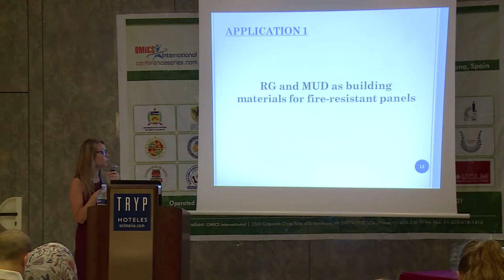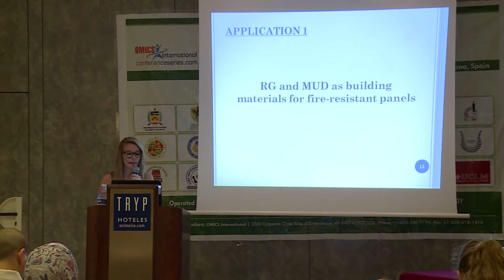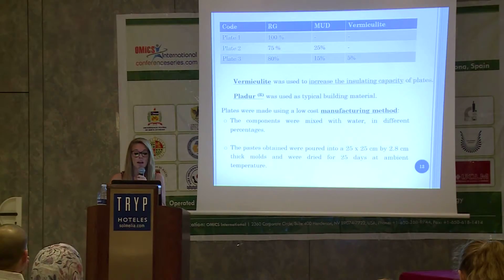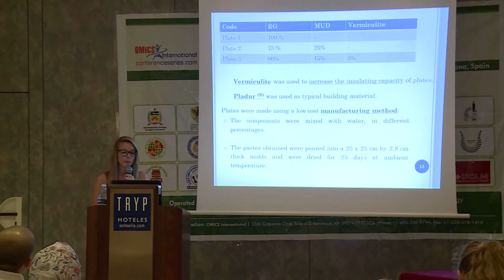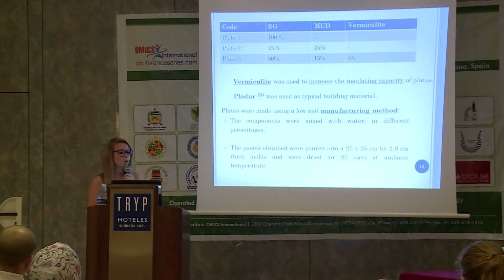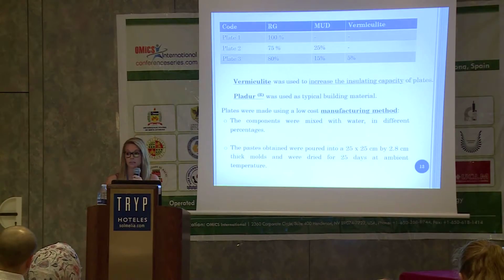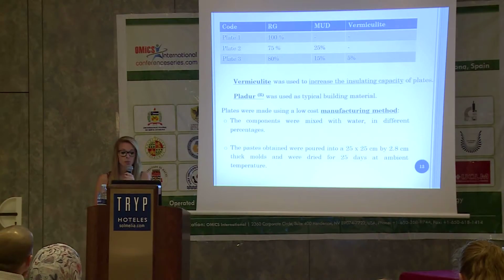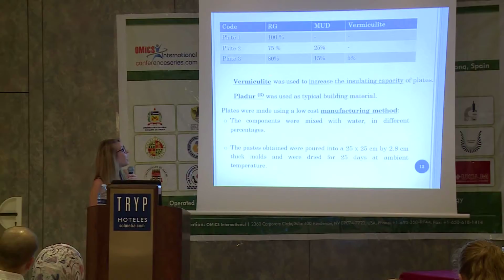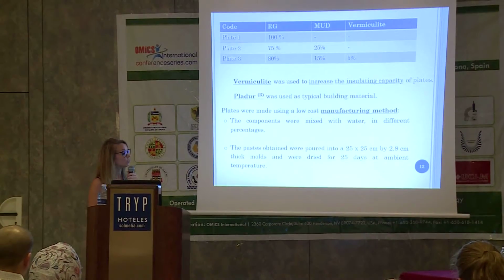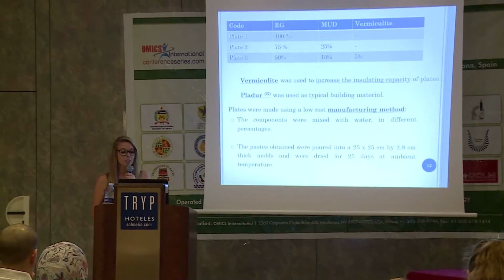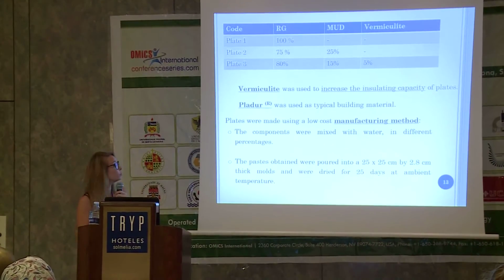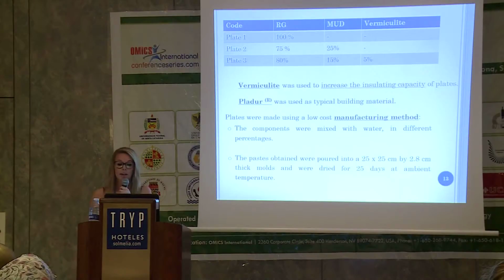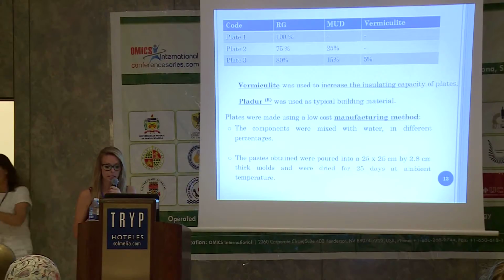I will explain the first application, which is red gypsum and mud as building material for fire-resistant panels. For this application, 3 plates were manufactured. Plate 1 is with red gypsum, 100%. Plate 2 with red gypsum, 75%, and 25% of mud. And plate 3, 80% of red gypsum, 15% of mud, and 5% of vermiculite. Vermiculite was used to increase the insulation capacity of the plates, and these plates were compared with pladur, which is used as a typical building material.